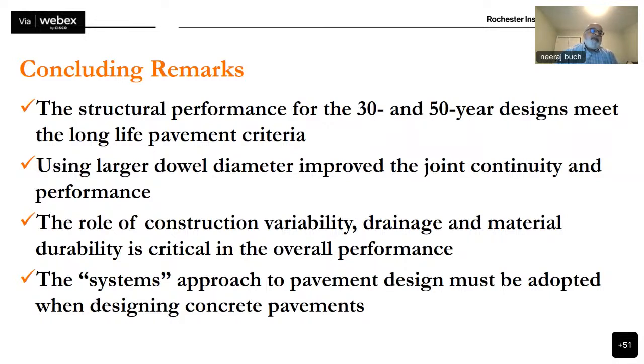Yeah, in that case, probably there is a revision required for the codes of practice in India. Yeah, at least in the US, we don't target more than 3,500 PSI or 25 megapascal, unless there is something really special that needs to happen, then there might be exceptions. But the rule is, 3,500 PSI is about the right compressive strength needed for paving concrete. So if the temperature variations are more, then you'll have to increase the thickness of the slab.